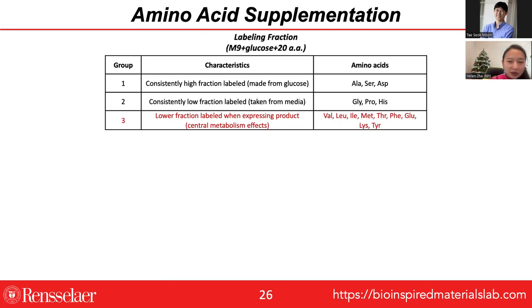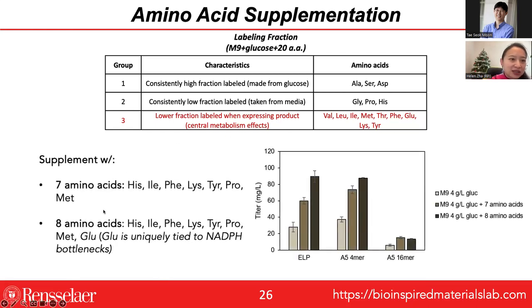Interestingly, we also attempted to supplement our media with some amino acids. We looked to supplement the media with the amino acids that are made by the cell, not taken up from the media naturally. So they are made by the cell if the cells are expressing our recombinant protein, as opposed to being taken up from the media. We tried supplementing with these 7 amino acids, which we've noted to have low C13 fraction labeling, which means that the cell is trying to make them, as opposed to taking the majority of them up from the media, meaning they are probably depleting them in the media. So we supplemented with these 7 amino acids.